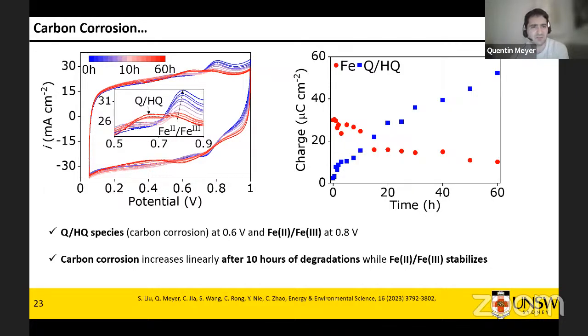What we carried out is some carbon corrosion characterization using cyclic voltammetry. So cyclic voltammetry is a technique where we saturate the cell with hydrogen on one side, on the anode side, and nitrogen on the cathode side. So hydrogen becomes a pseudo reference electrode. Nitrogen is used for a neutral environment, and we just sweep the voltage, and we see multiple peaks.